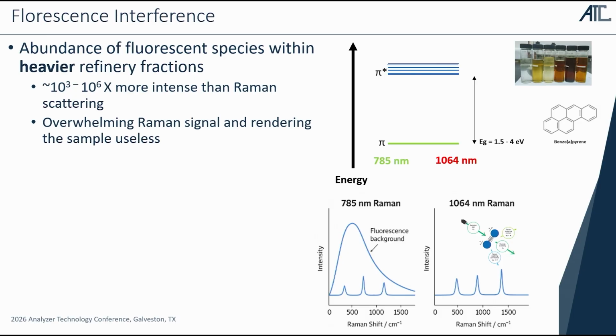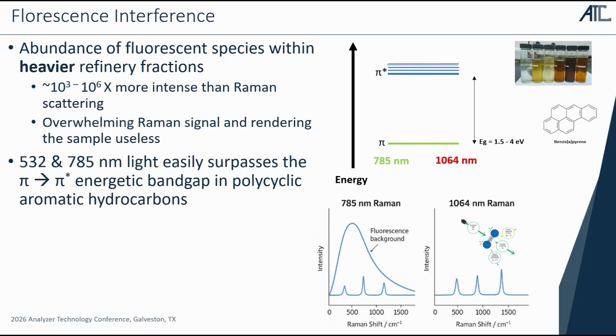The primary component that is causing this issue is these polycyclic aromatic hydrocarbons. These molecules love to absorb 532 and 785 nanometer light. They love to absorb it, and they love to re-emit it at a significant intensity. And so we're still interested in quantifying and observing those with Raman, but the fluorescence essentially renders them useless for